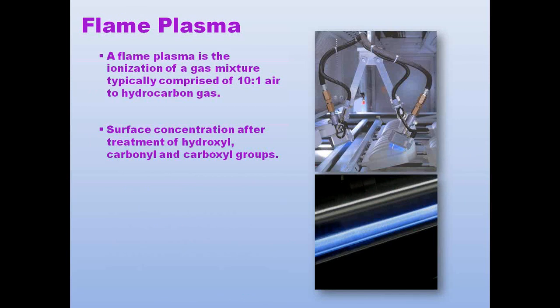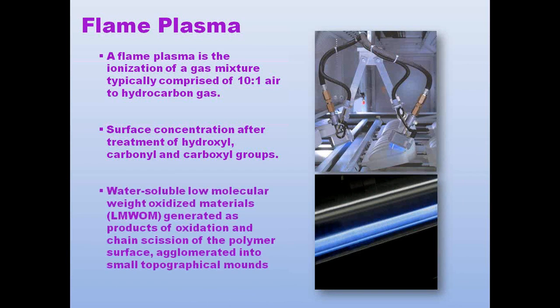Let's talk a little bit about flame technology. Flame technology has evolved over time and has become a much more useful and much more controlled process with regard to both three-dimensional objects as well as planar and roll-to-roll materials. It is a gas mixture typically of methane gas and air. The stoichiometric ratio is usually about 10 parts air to 1 part gas. The gas, again, can be methane or natural gas. It can also be butane or propane. If it is the latter of the two, it is typically then a change in the air component by a factor of 2 or 3 to ultimately completely combust the specific type of hydrocarbon gas that's being used. After that treatment, however, you are getting a carbon-based functionality, typically hydroxyl, carbonyl, and carboxyl groups.